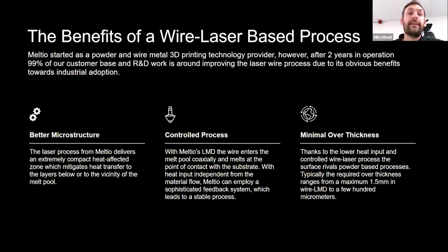So the microstructure is tighter, and the overall density of the parts is better. As I mentioned earlier about the process control system, we have a really highly controlled welding process. So the normal to the surface wire and the constant contact with either the substrate or the part allows the current to flow, which we can then use to not only monitor the print, but with some of the upgrades as well to the system, we can put a hot wire through that wire, through that current. So we can heat the wire using resistance rather than just the lasers and speed up the production process even